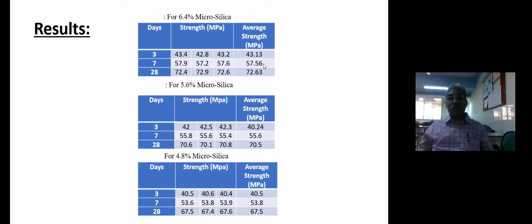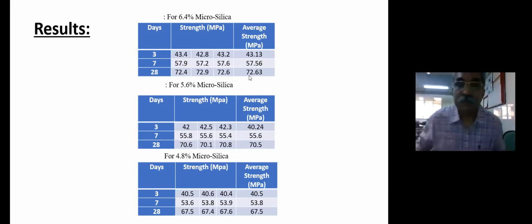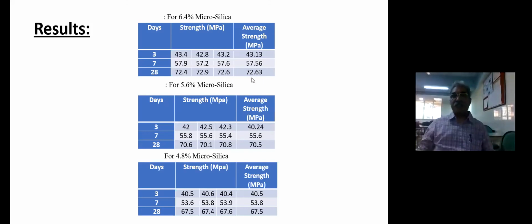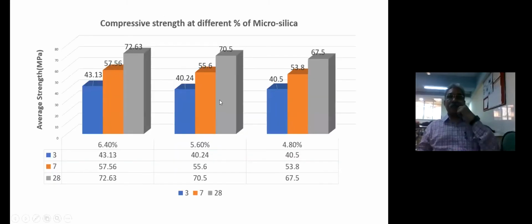72.63. So it is M40 concrete, and we are getting 72 against 40. So it is almost double. Not double, so we can take it as a 1.8 times increase in average strength. And this was the maximum we got at 6.4, and at 5.6 it was less, and at 4.8 it was even less. So we have decided that we will use 6.4% microsilica. Then this is the comparative strength chart. The same thing is depicted here in the form of a chart, that we got this 72.63.